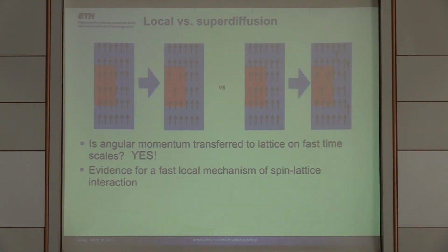I'm sorry, Steve, question. Yeah. What you showed here, is that a Bragg peak that's shifting, or is it a structure factor? You can't see the Bragg peak because it would appear below the sample horizon. So we're looking at wings of a Bragg peak. If you have a normal thin film diffraction, you see a peak, and then you see these bumps. So we're looking only at these oscillations up at the top. What we're doing is analyzing intensity changes to these wings, these Laue oscillation wings. And those are sensitive to the phonon.